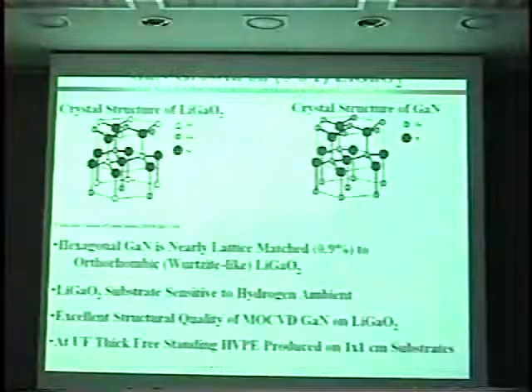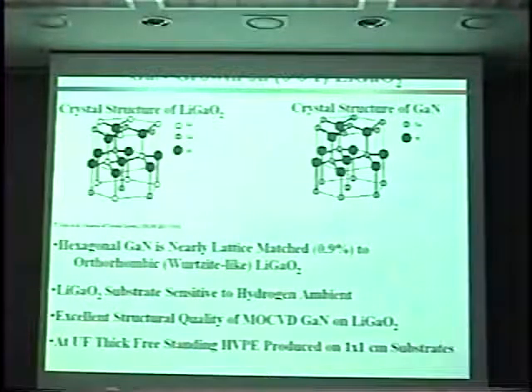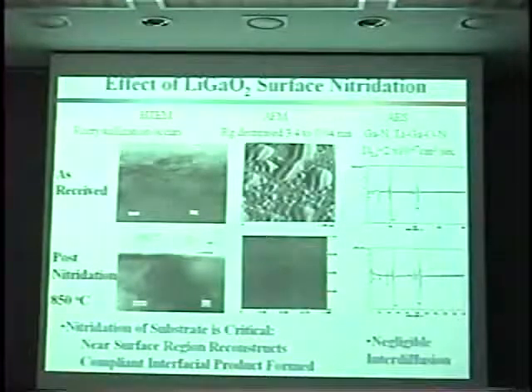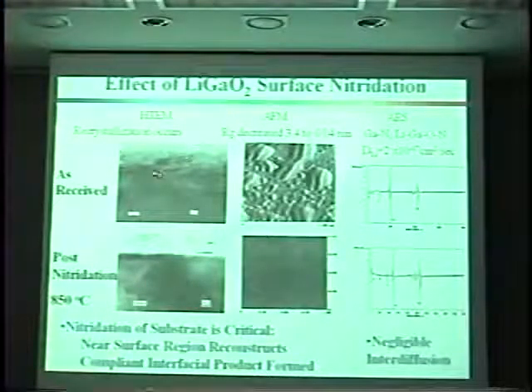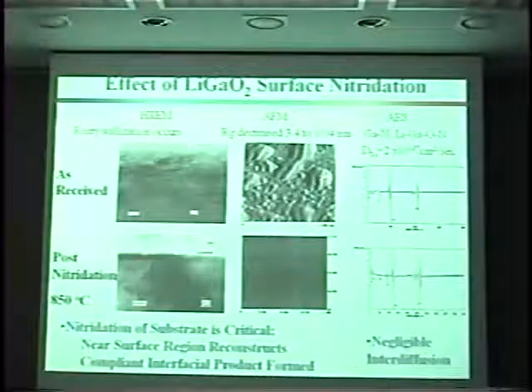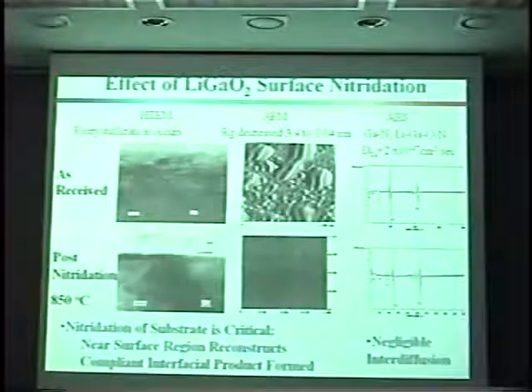Here's the crystal structure of LGO. It's orthorhombic, but it's nearly hexagonal and has a very small mismatch to gallium nitride. Here are some results that compare some of our first attempts. We would take as-received LGO. It was just being produced and was not available commercially when we started. You can see the top surface is not crystalline. There's a lot of damage. The polishing procedures were not in place.